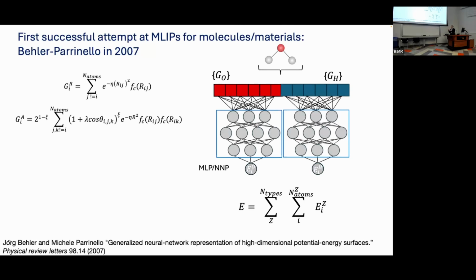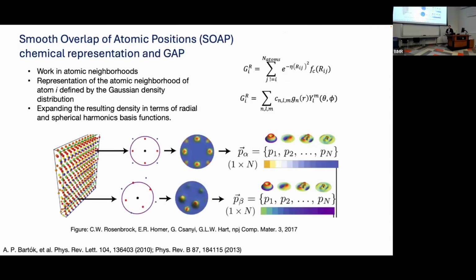This seems quite obvious now, several years later, but at the time, this was a pretty clever idea in order to successfully train these neural networks so they could be applied to atomistic systems. And the field in general has recycled this idea over and over, not just in terms of the sum of the local energies, but also of the representations. One example of that: these are neural network-based ones, but if you replace the neural network with, for example, a kernel ridge-based algorithm, then you have what Gábor published in 2010 with Albert Bartók in the GAP framework, with the SOAP representation, sorry.